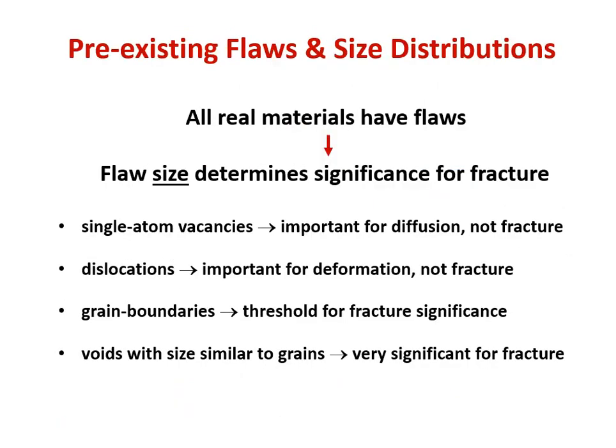So as we were saying at the beginning of this section, all real materials have flaws, and the flaw size determines the significance for fracture. So again, these are not single atom vacancies. Those are great if we're going to do alloying. They're important for diffusion, as we noted in our mass transport section, but that's too small to really have a big effect on fracture. Dislocations are a little bit bigger, and they're really important for deformation, as we learned in our strengthening section, but again, they're too small to really have an effect on fracture.